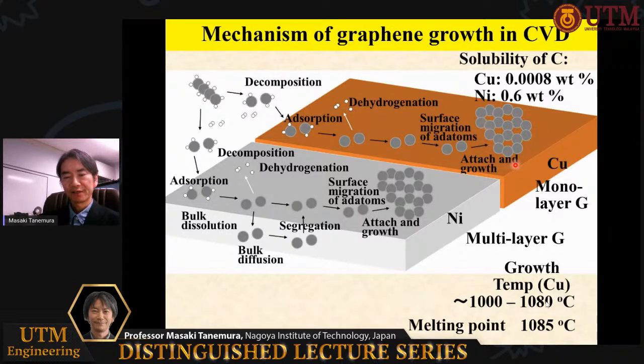On the nickel surface, additional bulk diffusion of adsorbed carbon atoms and segregation to the surface occur because the solubility of carbon is much higher for nickel than copper. So copper is suitable for the monolayer graphene growth, and nickel is suitable for the multilayer graphene growth.